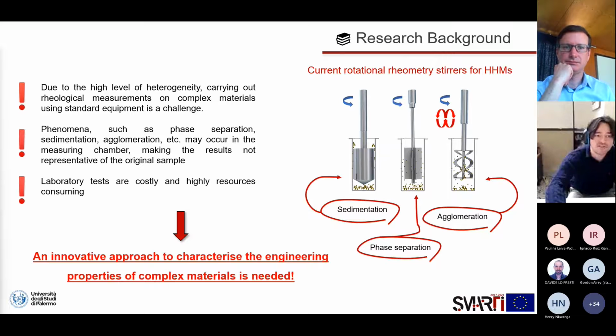This exercise to define the dynamic viscosity is usually carried out in laboratory by using a rotational viscometer. However, due to the high level of heterogeneity, carrying out rheological measurement on this kind of material using standard equipment might be challenging. Indeed, phenomena such as separation, sedimentation, and agglomeration may occur within the measuring chamber, making the results not representative of the original sample. Also, laboratory tests are costly and highly resource consuming. Therefore, an innovative approach to characterize the engineering properties of complex materials is needed.